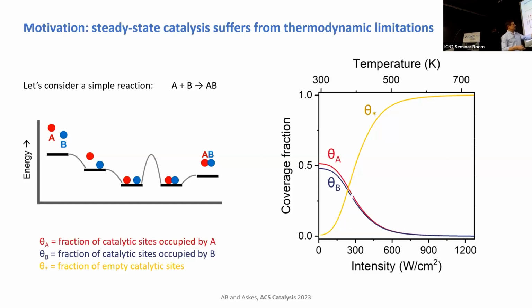And the problem is that if you are at room temperature, there is essentially no energy to overcome this activation energy barrier. And then what you do is, okay, now I'm going to heat up my catalyst in order to give it enough energy to form the products. But if you heat up the catalyst, then the surface coverage of A and B will go down and the fraction of empty sites will go up. And so now you have enough energy for A and B to react with each other and form the product, but there is no A or B on the catalyst.